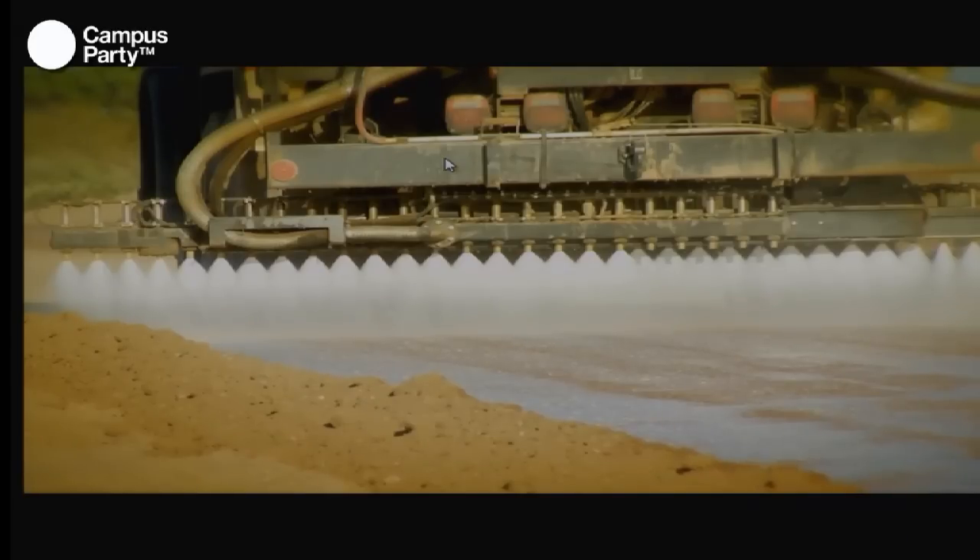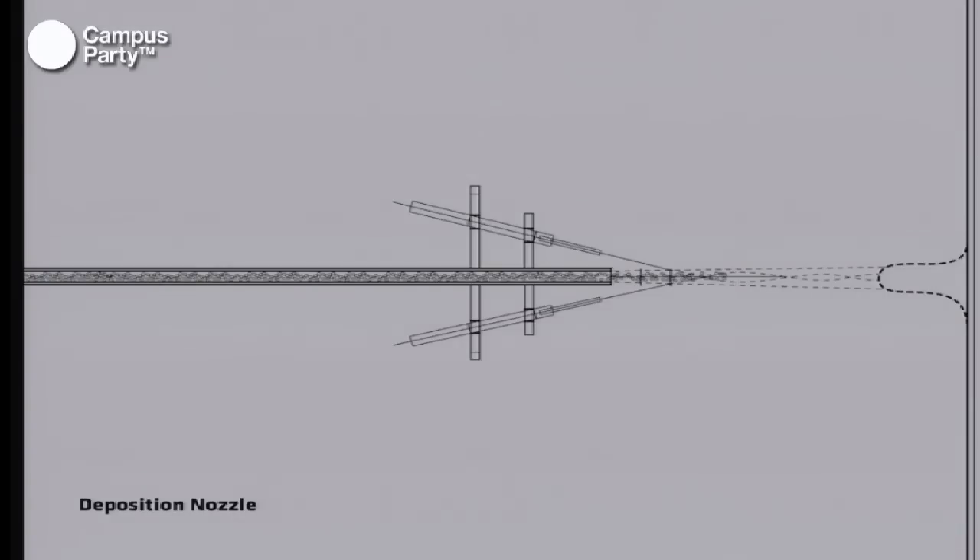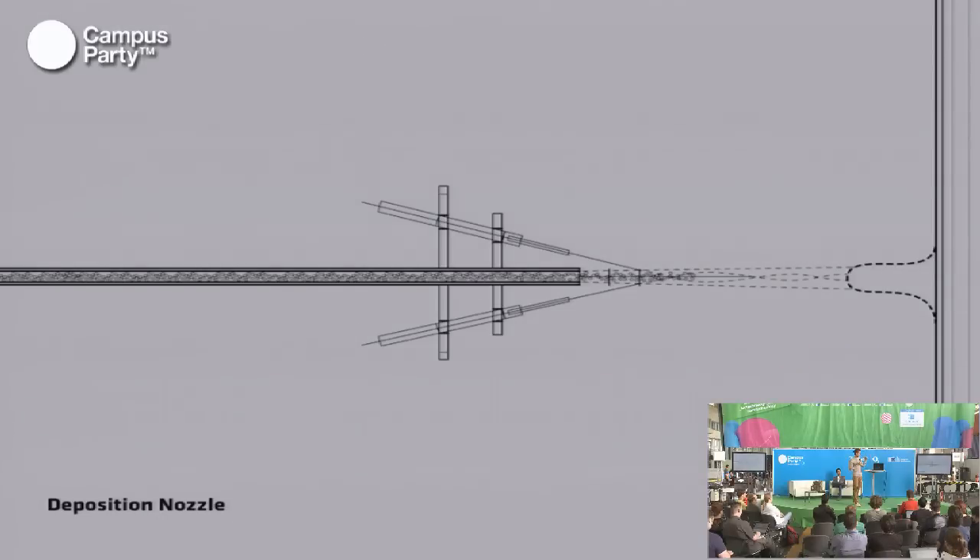The question is how you actually make a 3D printer with these two components — sand and this binder. We did a lot of experiments and invented a nozzle that, with air pressure, pushes the sand from one jet spray, and from the other two jet sprays pushes the solidifier components. They mix together in mid-air and fall on the targeted surface, creating a solid object. Interestingly, you can spray the material not only vertically like conventional fused deposition modeling printers do, but on vertical surfaces too — so you can actually add structures to already existing structures.